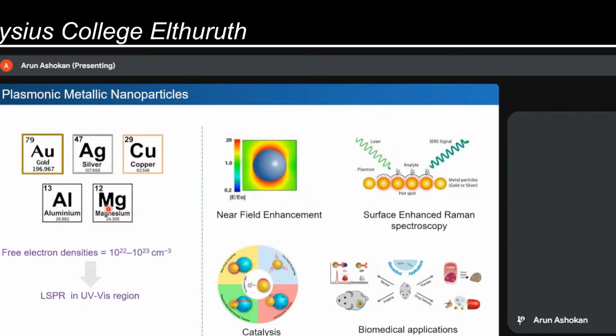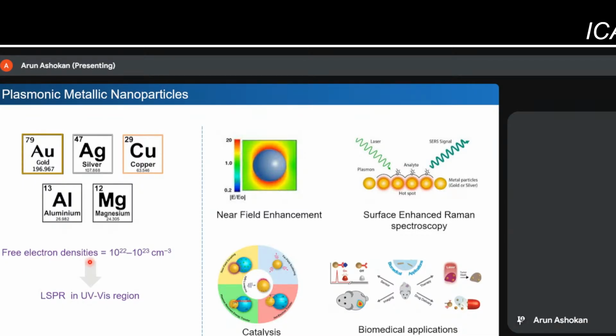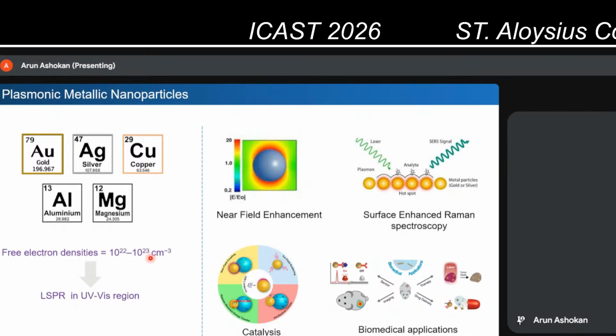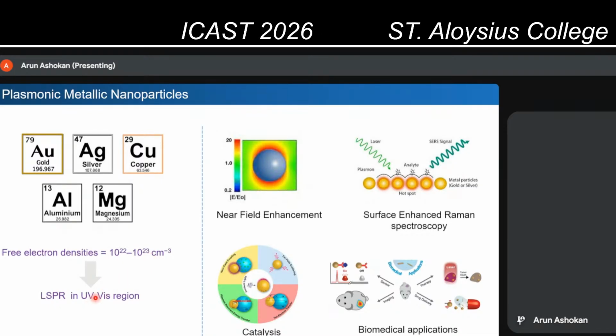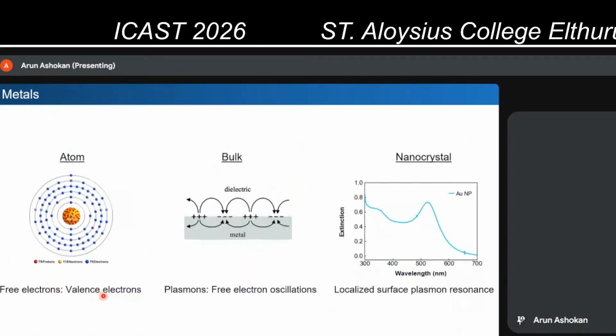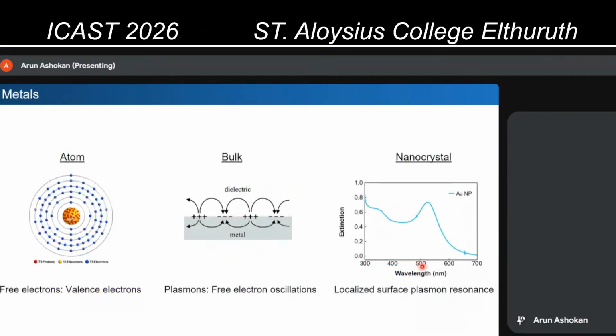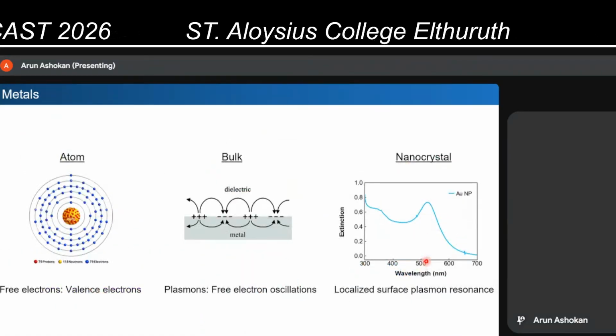So the interesting property here is the free electron density. The free electron density is what actually controls the plasmon. In this case, for metals, the free electron density ranges from 10^22 to 10^23 per cubic centimeter. And this results in a plasmon frequency in the UV-vis region. For example, in the case of gold nanocrystals, you can see it's in the visible region.